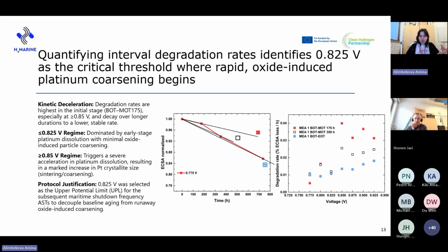Then we analyzed further the degradation rates across the testing intervals. So we plotted the degradation rates versus the holding voltages, basically the slope between the beginning and the middle of tests and then end of tests. This data shows that there is also a clear time-dependent slowing down of the electrochemical surface area loss, where in the initial stages of the accelerated stress test, the degradation rate is quite high, and then it slows down and becomes more or less even across all voltages.